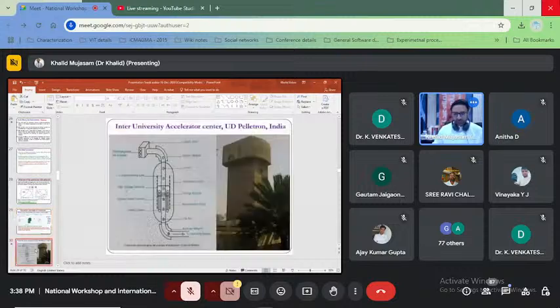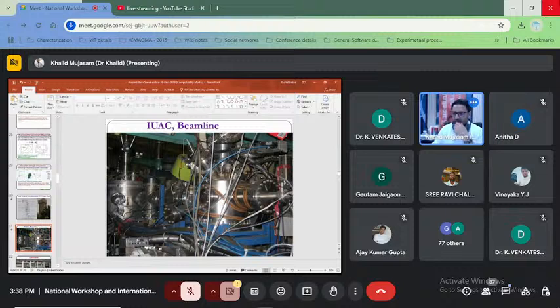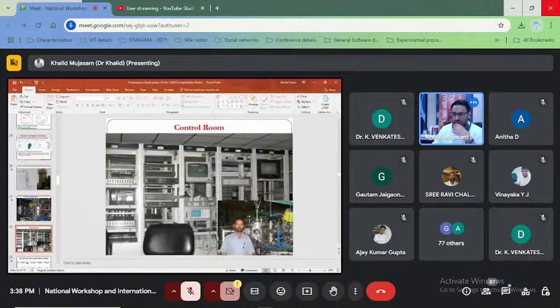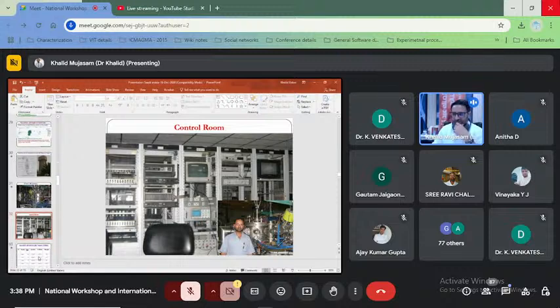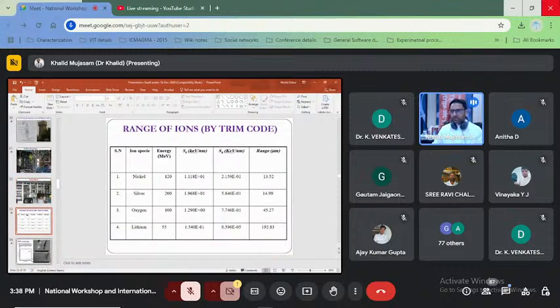This is the 15 UD Pelletron Accelerator Center in New Delhi, India, and this is the materials beam line in its basement. You can see the control room, where I worked long back, and my face looks very different; this is one of the oldest pictures I am using. From the different ion beams we chose nickel, silver, oxygen, and lithium. As I mentioned, you have to calculate the electronic and nuclear energy loss values, and accordingly determine the range of the beam, where it will come close to your substrate, and how the damages are going to happen.